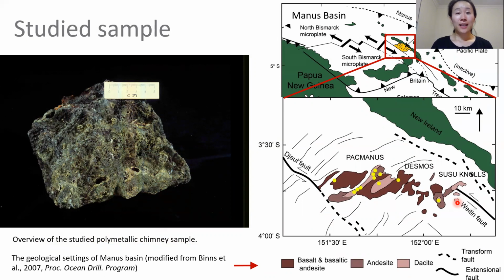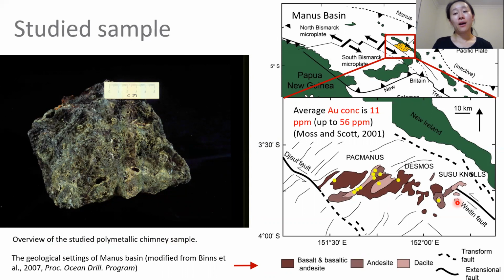The sulfide chimneys contain elevated gold in this area. The average concentration of gold is 11 ppm, with the highest up to 56 ppm. However, in previous studies, it's generally very difficult to quickly locate the native gold because it's very tiny in the sulfide. And you may have to spend a long time looking at them with the optical microscope. So in this study, we applied a combination of synchrotron XRF elemental mapping and also EBSD microstructure and crystal mapping to locate the gold and try to figure out its precipitation mechanism.